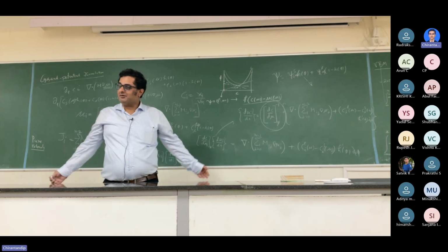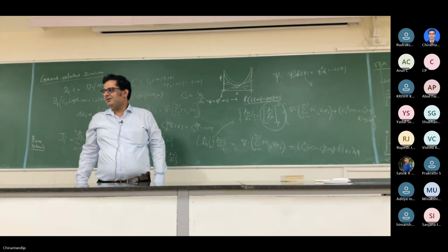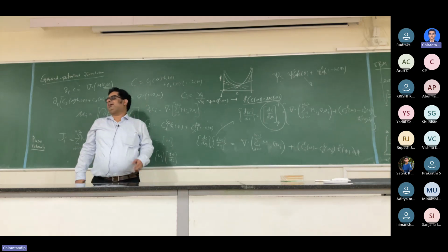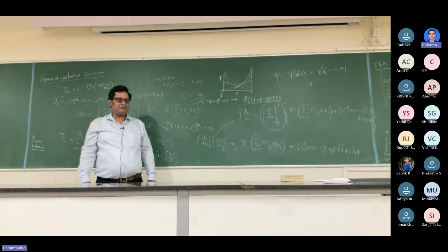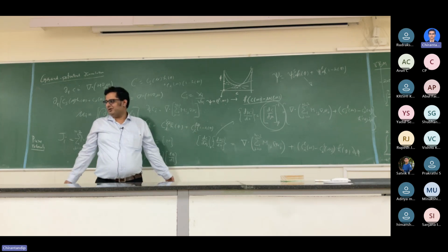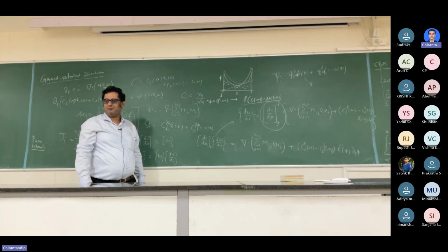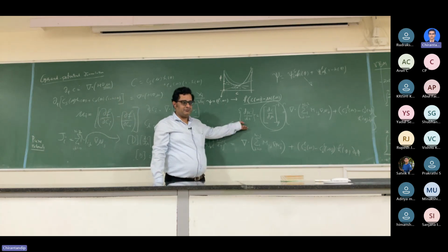But as the number of components goes up, we'll have to do the matrix inversion all the time. So basically, from the KKS, which had an iterative solver with multiple matrix inversions inside, we have reduced it down to one single matrix inversion. That's okay in terms of computational effectiveness. So this is how your multi-component diffusion equation will look.